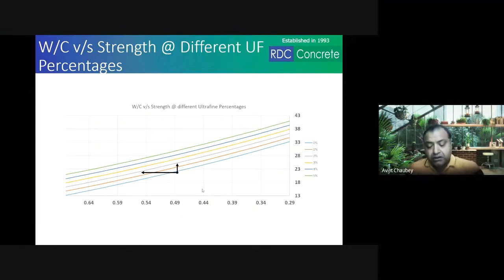And that is the reason why you tend to get better rheology. One thing, let me clarify: if you keep the same mix and just replace the cementitious with ultrafine, don't expect that you will get lesser stickiness. You will get lesser stickiness for the same strength when you are able to change the water cement ratio, when you're able to change the mix, when you're able to make use of the properties of ultrafine minerals. If you're able to utilize those properties, then you will tend to get a better mix with better workability, better pumpability, and better strengths. You need to know how it behaves, and based on that you do your mix.